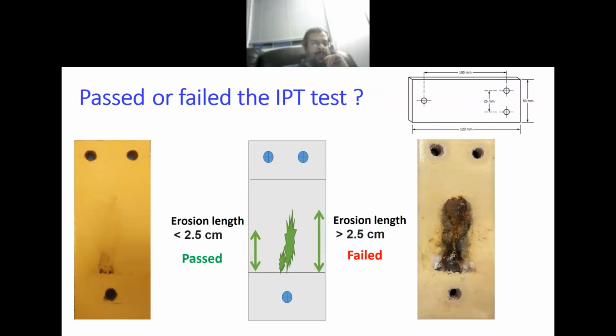Now, these are two samples. This one is the passed one, and to the right is the failed one. You can see here some traces of tracking and erosion. Now, what is the criterion for pass and fail? If the length of this arcing from the ground end, which is this side, to the top is more than 2.5 centimeters, we consider this material failed. Or if there is a puncture in the material. Sometimes we don't have this long erosion, but we have a concentrated arcing that will lead to puncture of the material. So this material will be failed.